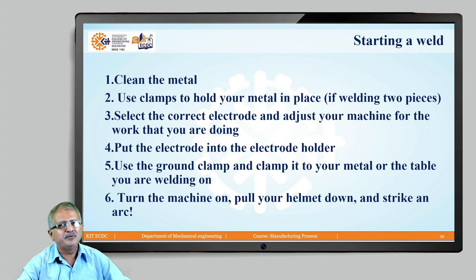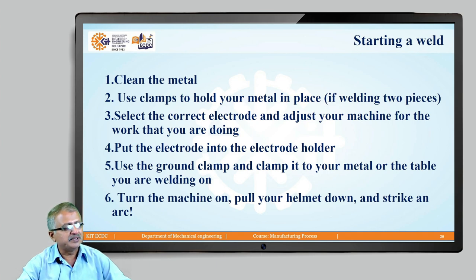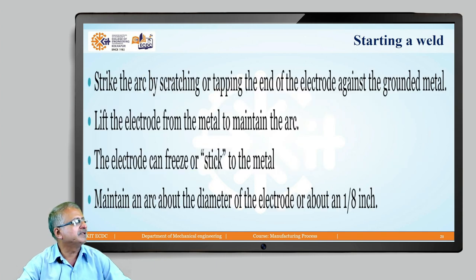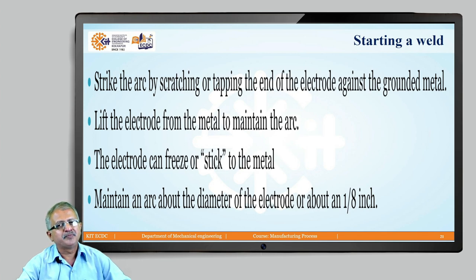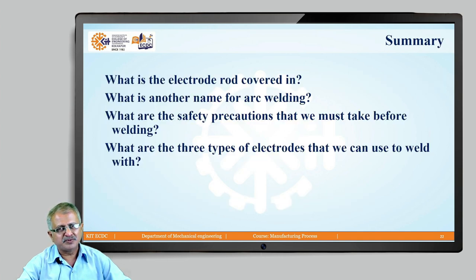A simple SOP for carrying out arc welding: clean the base metal and prepare the edge, then clamp the metals. Select the correct electrode and adjust the machine settings. Put the electrode in the electrode holder, use the ground clamp on the metal, turn the machine on, pull your helmet down, and start striking an arc. Once the arc is struck, take the electrode slightly away from the base metal — the gap ionizes to form plasma, providing sufficient heat to melt the weld zone edges. The flux coating melts first providing a slag cover, then the core wire provides the required composition to the joint.